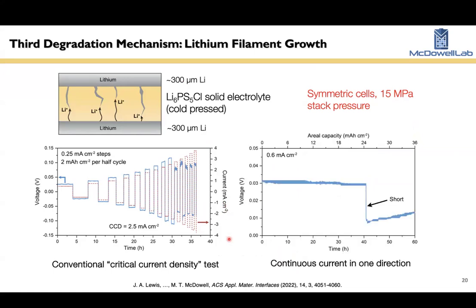And one of the things that we found that was kind of interesting, this is especially for the experts in the audience, if you have a normal sulfide type solid electrolyte, like an argyrodite Li6PS5Cl material, usually people make these into batteries by cold pressing them, and there's some density associated with the cold pressed body, usually around 90% or so. It can be a little better, but they're somewhat porous. They have high conductivity, but they're somewhat porous.